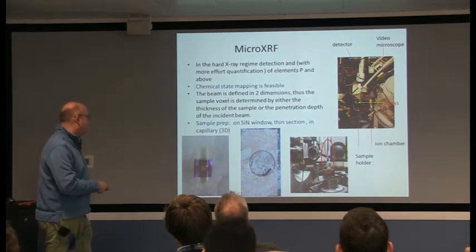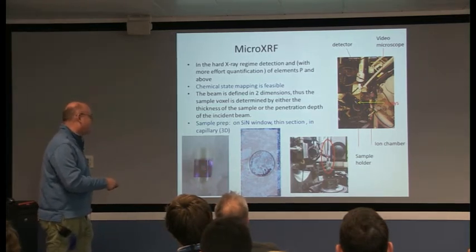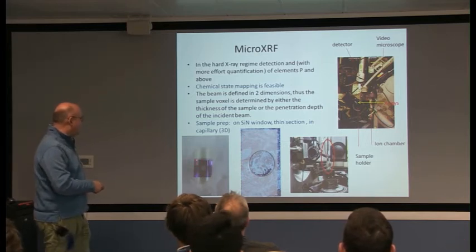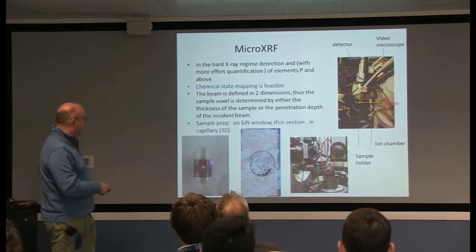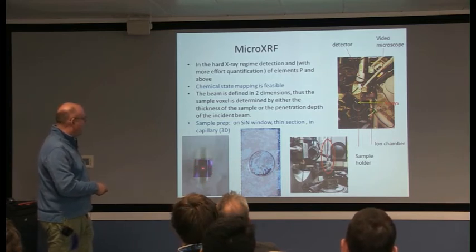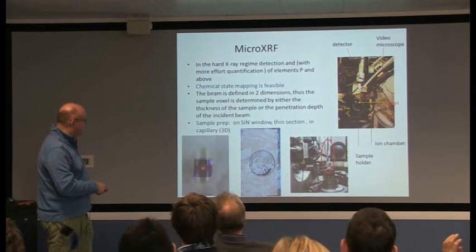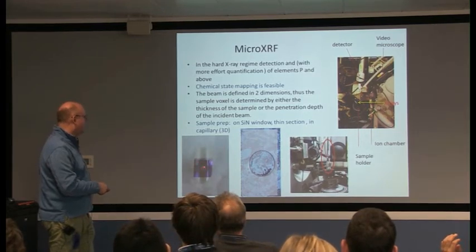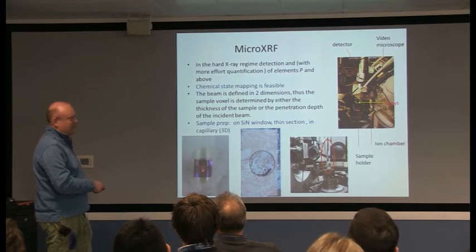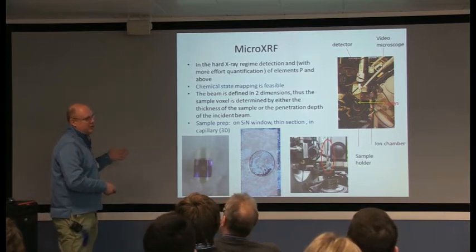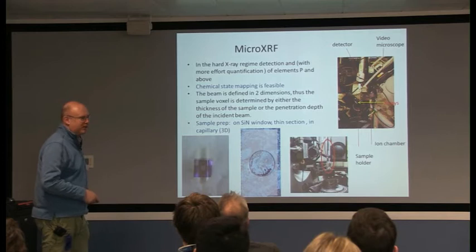And then this is a silicon nitride window - that's a standard slide, I think a 2-inch by 1-inch slide. This is a 10 millimeter silicon nitride window with a 200 nanometer membrane. The slide itself is probably a millimeter thick, but it's got a window which is 200 nanometers thick, so you can put grains of dust or whatever on there and do diffraction as well in the same way.